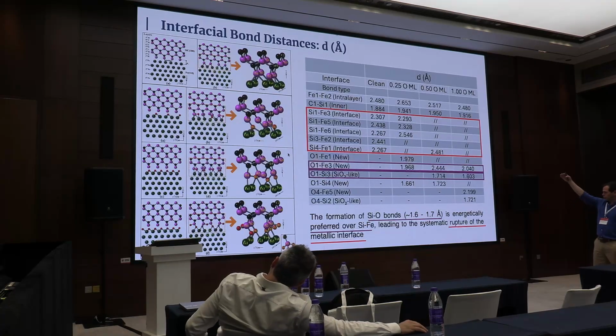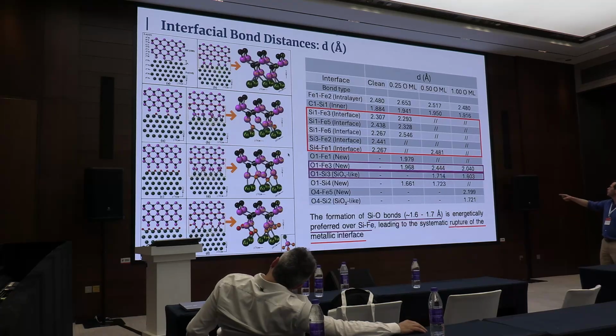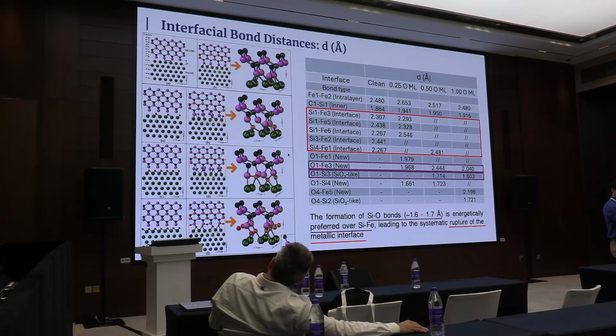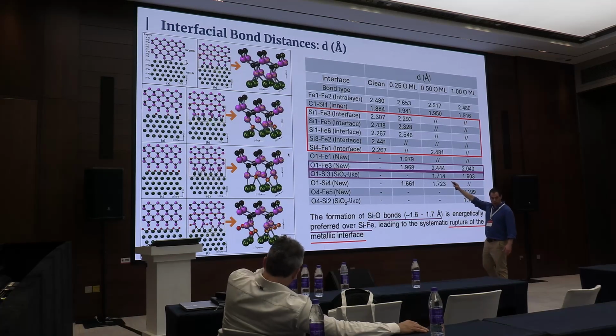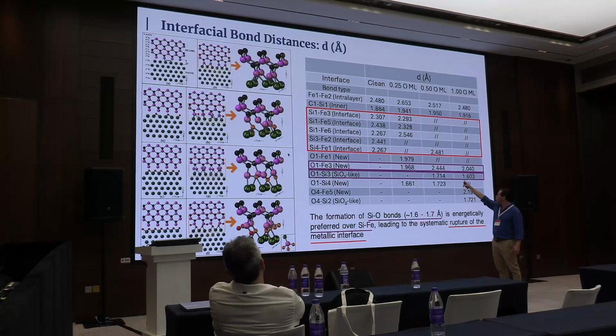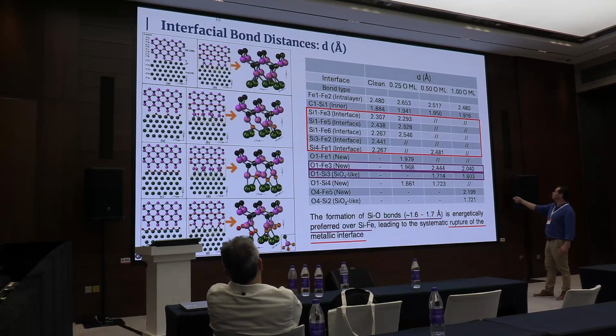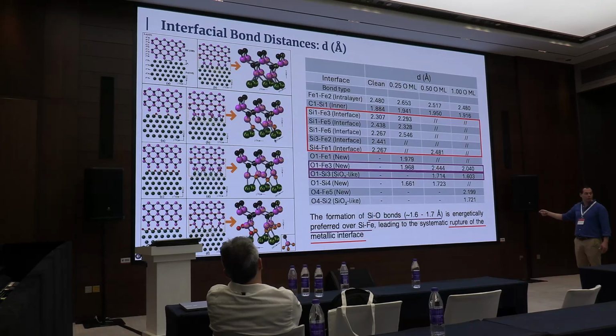For the systems, as soon as we increase the oxygen, we can observe here we are showing the distances between atoms. If you see the numbers, for example, some atoms at the interface are iron and silicon directly bonded. If you see here, all the links have numbers, but as soon as an oxygen appears, two are disappearing there. Here, two connections, two bonds disappear. When we have more oxygen, almost all disappear, and we have here a full monolayer, and all the iron silicon interactions have disappeared.